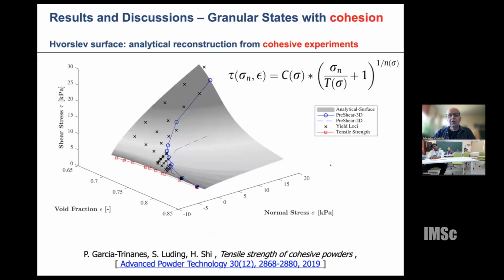One example of our work where we did some experiments was the tensile powder testing. And we were bringing the new experimental results and old experimental results together. The gray surface is a classical thing from 70 years ago, the so-called Hvorslev surface, and it brings all the experimental data on this surface: shear stress on the vertical axis, density, which you can call by different names, on another axis, and normal confining stress on the axis to the right.